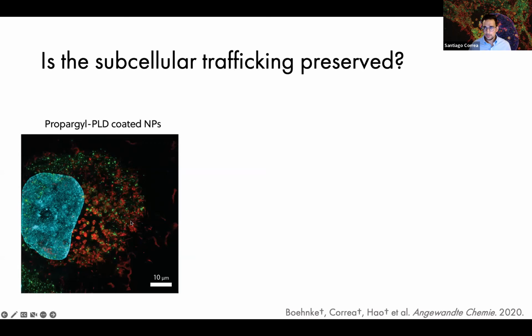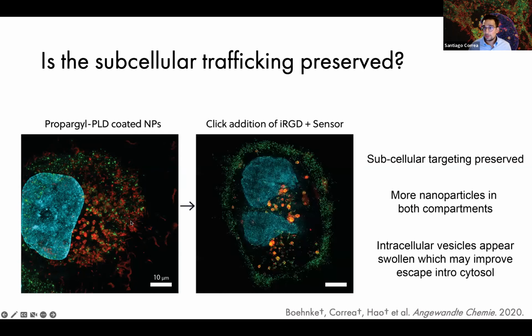What was really exciting was that we also evaluated this for our click modified nanoparticles. And we saw that when we introduced the iRGD targeting ligand and the biosensor peptide, we are seeing much higher accumulation of nanoparticle in both compartments. So we were preserving that unique subcellular trafficking profile, but just seeing a lot more nanoparticle in both places. And in particular, I'll draw your attention to the intracellular nanoparticle accumulation. If you compare these vesicles from left to right, you'll notice that the vesicles on the right are much larger, almost as if they're engorged, which we hypothesized would actually lead to improved gene silencing, since this would likely lead to leakier vesicles over time.